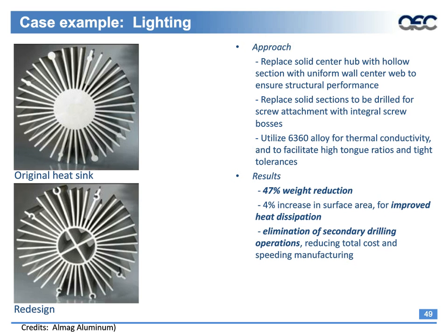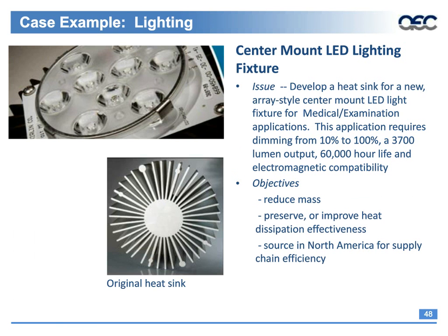The one above, the original one, was solid. The part would get cut and then anodized, and they would drill and tap so that they could mount the LED modules on here. But with the redesign, it was redesigned to incorporate screw ports. So there was no drilling and no tapping that had to happen. They just had to switch to a self-tapping screw and then drive it in. So the result here was a 47% weight reduction and the elimination of secondary drilling operations, which reduced the total cost and gave the customer a good local source to speed up manufacturing.